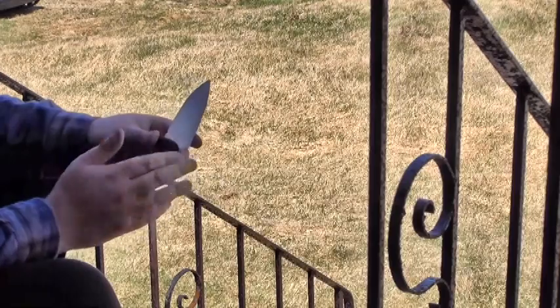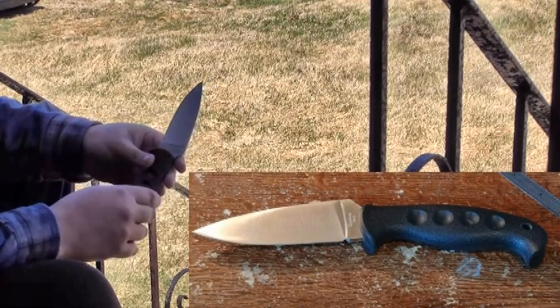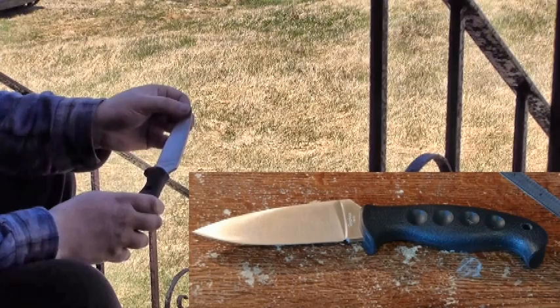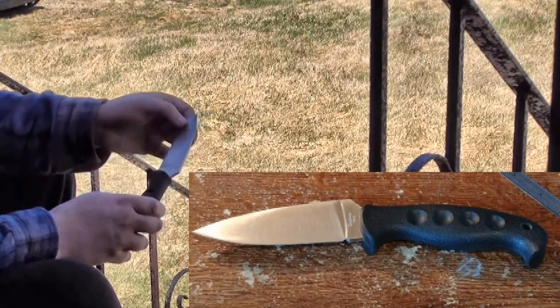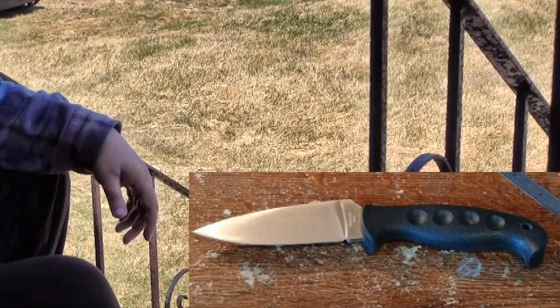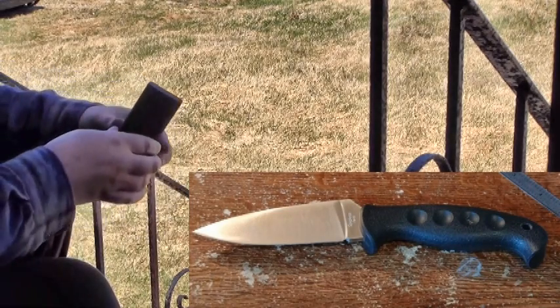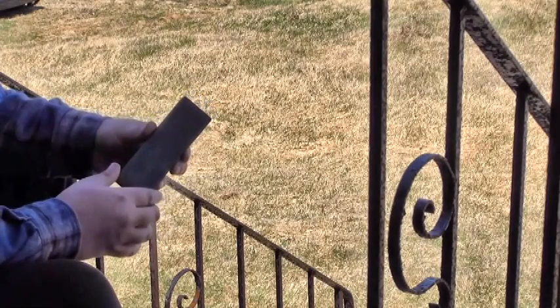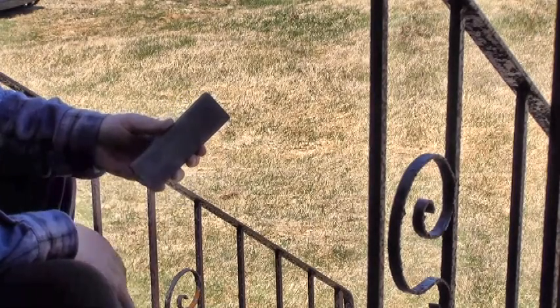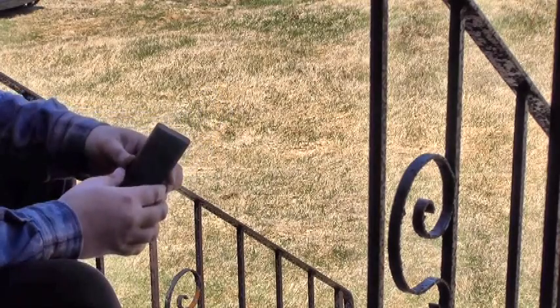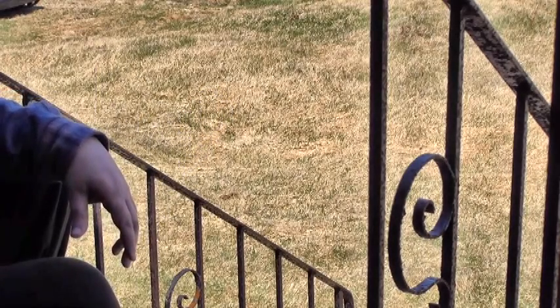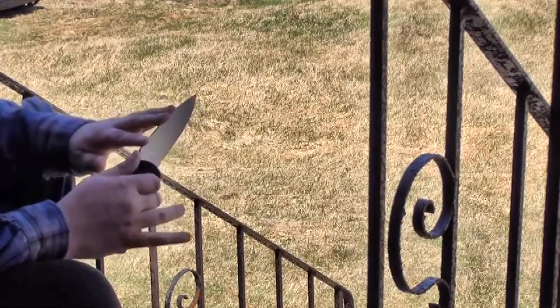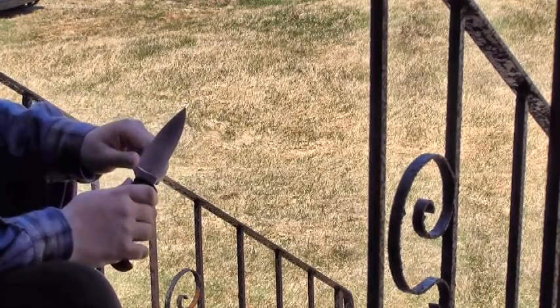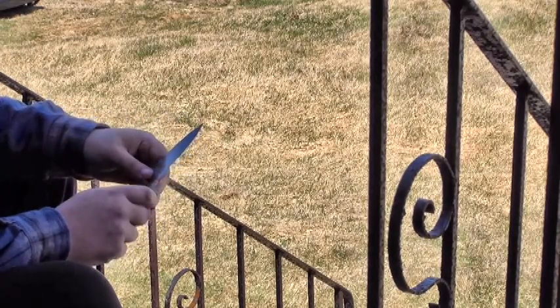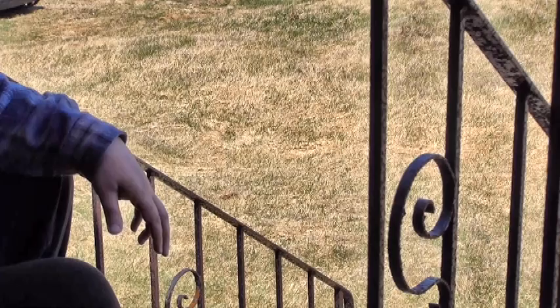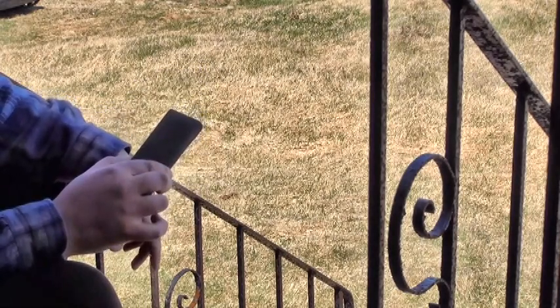As I mentioned earlier, this knife is very well used, years and years of use. The edge had thickened and widened out, and I reground the primary to get the edge under 5 thousandths thick again. And after I did that, I used this, which is one of the cheapest and worst cutting stones that I have, and within literally like 30 seconds, the edge on the Temperance was to the point where it was just about to start doing a true 90 push cut on newsprint and could easily take hairs off the arm,